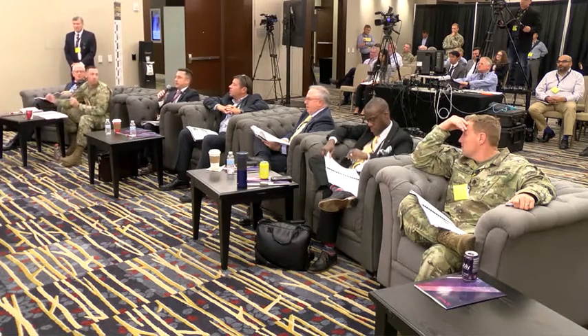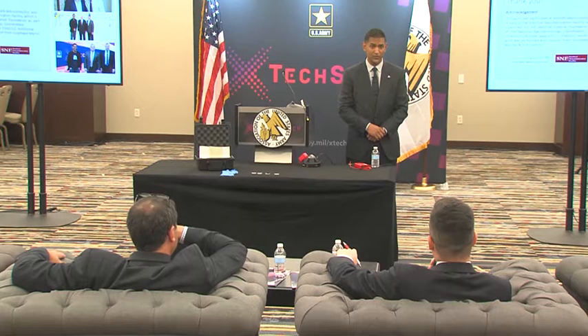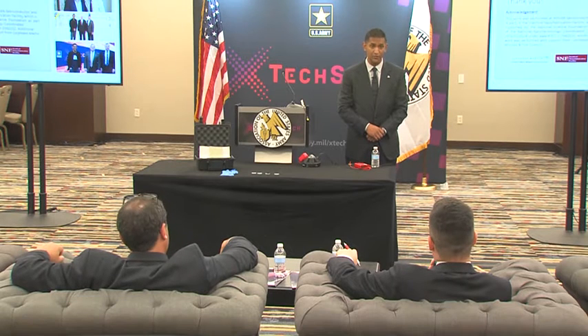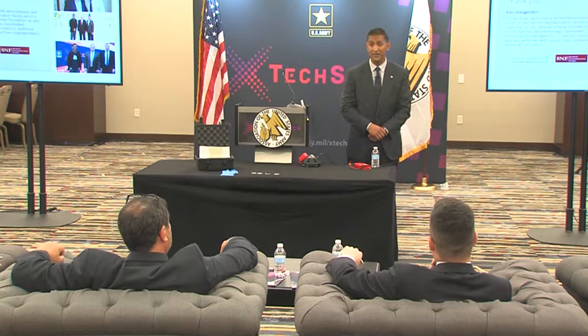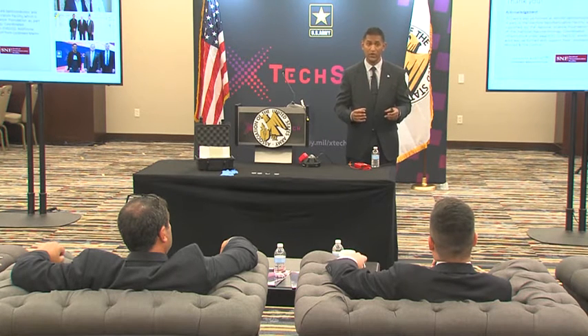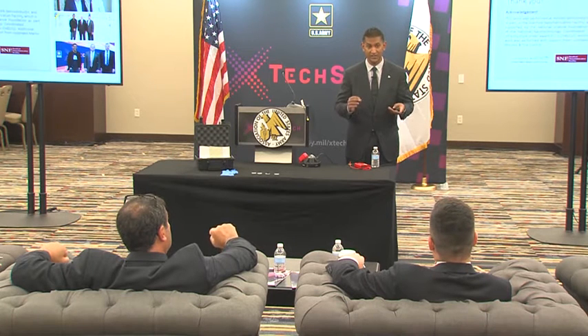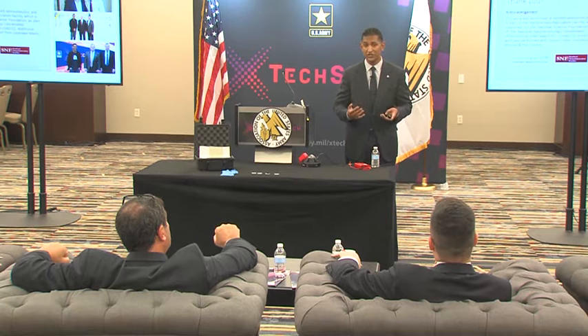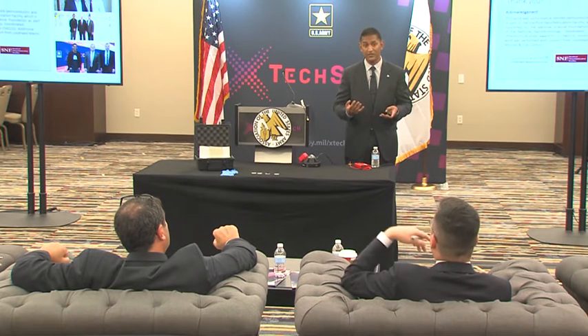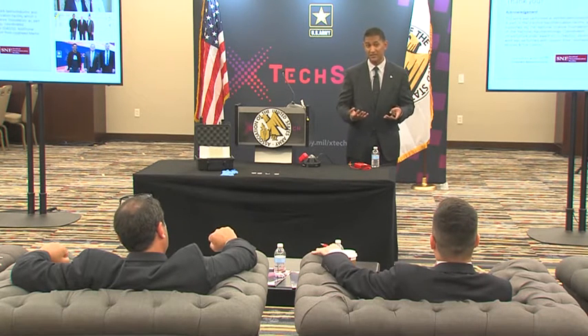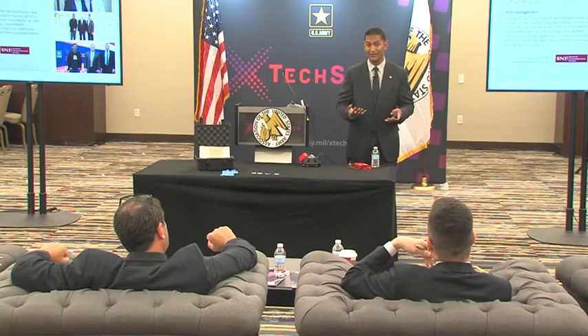What's the largest substrate that you can currently coat? In our current system, it's a 12-inch by 12-inch. We're planning to scale up this equipment size to go over 1 meter by 1 meter, so we're not currently constrained by any size in terms of the surface area. In terms of the thickness, we want to optimize the thinness of the material so it's lower cost at these very thin film structures. Additionally, because we're in the nano regime, we're talking about roughly 1/10,000th thickness of a human hair, so there's no weight modification by integrating such a system.